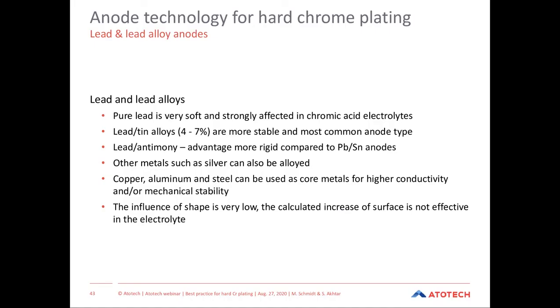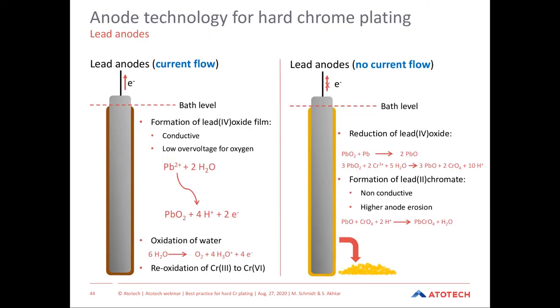Some words on the anodes. Typically, lead tin anodes are used with 4 to 7% of tin. Lead antimony is also of choice when the anodes get very long, because it's more stable, providing a more stable shape. And also silver was added in the past in order to fight chloride contaminations.